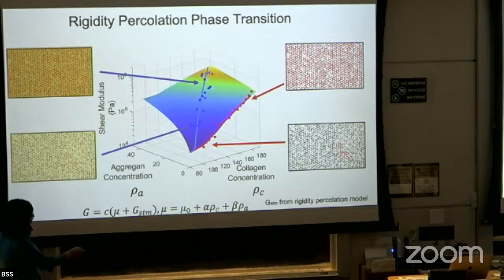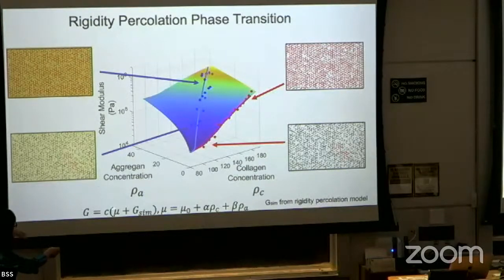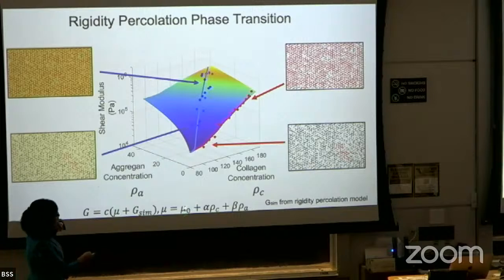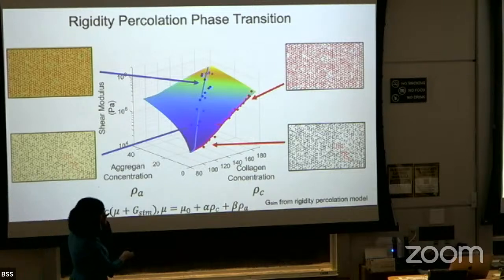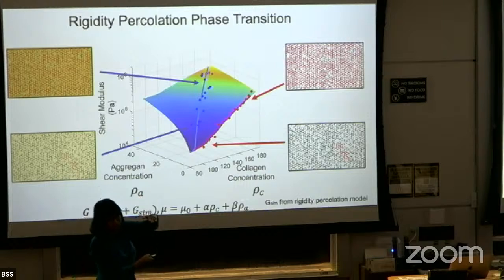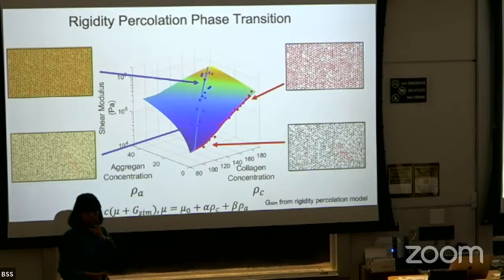So this is a part, I will show you what things map to. Basically, this is coming from the simulations, and then we have another elastic background, which is coming from the contribution of things that are not part of the network. You have a hyaluronic acid contribution that's the same throughout the tissue depth. We have a contribution from collagen, which are pieces of collagen that are part of the background gel that can change with height. And then you have aggrecan that are part of the background gel that is also going to change with height.